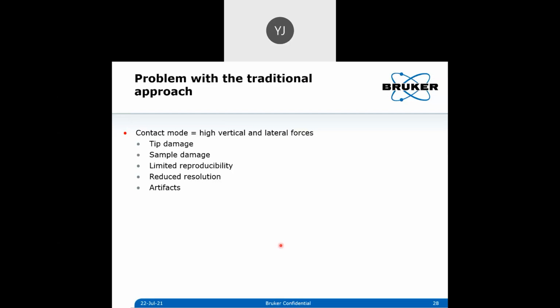So traditional conductive AFM, unlike KPFM, is based on contact mode technique, right? That means you have all the problems that come with contact mode. You have tip damage if your sample is hard. Remember, if you're doing conductive AFM, you're using a metal coated tip, and metal is generally a much softer material than something like silicon nitride, right? So if you're using this kind of metal tip to image semiconductor material, you have tip damage. Or if your sample is very soft, like a polymer material, you might have sample damage.